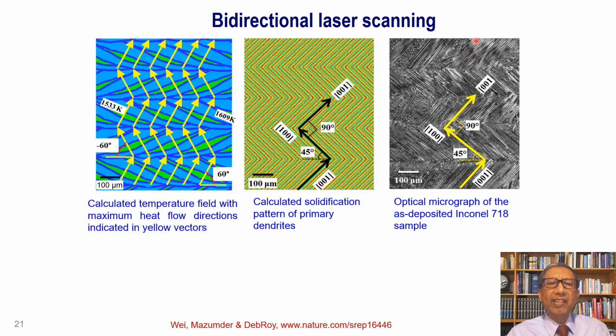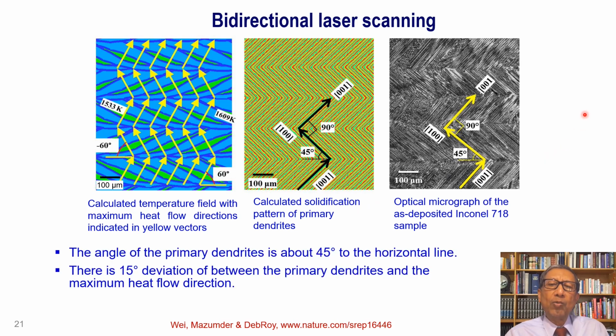Experimentally, what we see is that the growth directions of primary dendrites are at 90 degrees with each other. In each layer, the primary dendrites grow perpendicular to that of the previous layer. So there is a mismatch between the primary dendrite growth direction and the heat flow direction. The heat flow direction is 60 degrees with the scanning direction, but the primary dendrite growth direction is about 45 degrees with the scanning direction. So let us examine why that is so.